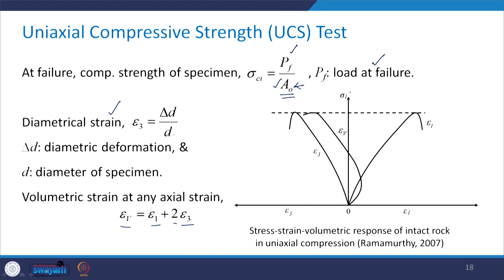So if we plot the stress strain and volumetric response of the intact rock in the uniaxial compression test, this is how it looks. On the x axis, on one side you have epsilon 1, on the other side you have epsilon 3, and on the y axis you have the stress, sigma 1 prime. This is how the axial strain varies. This is the variation of epsilon 1, this is the variation of epsilon 3, and this is the variation of the volumetric strain. So that's a typical stress strain volumetric response of the intact rock that you will obtain in the UCS test.